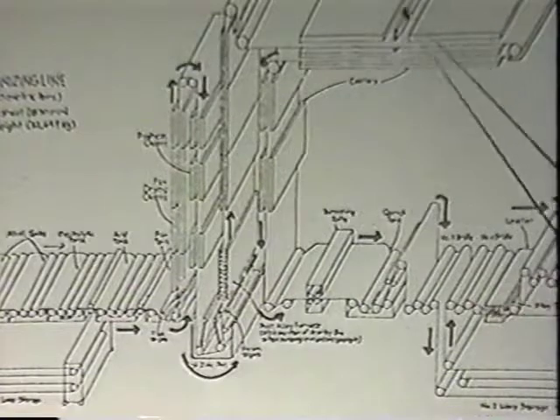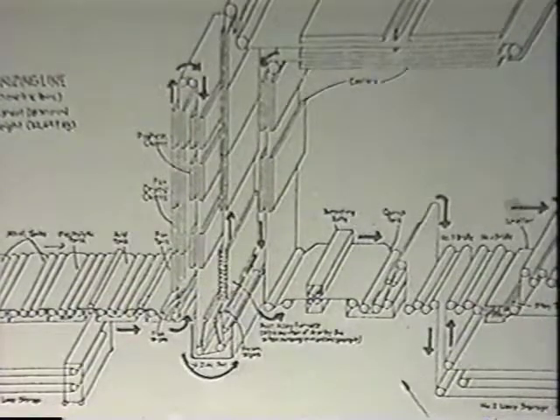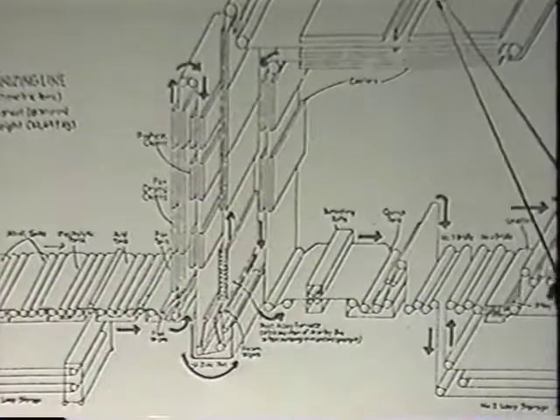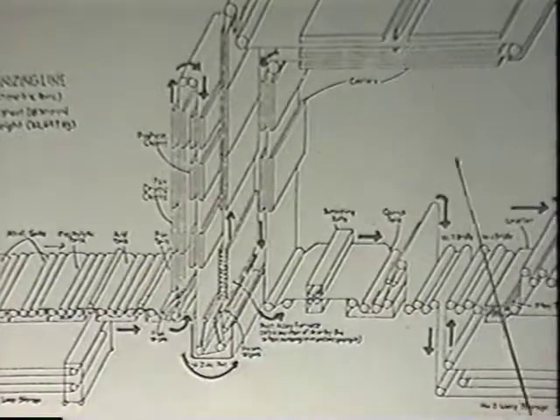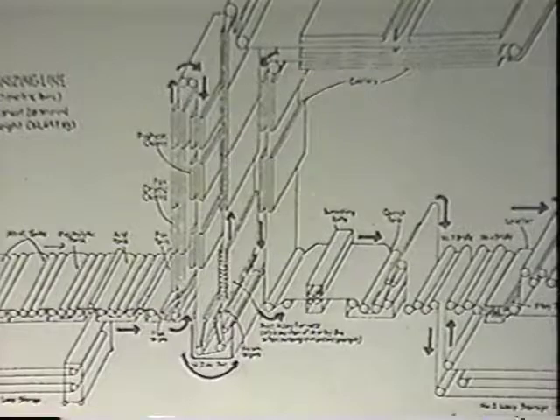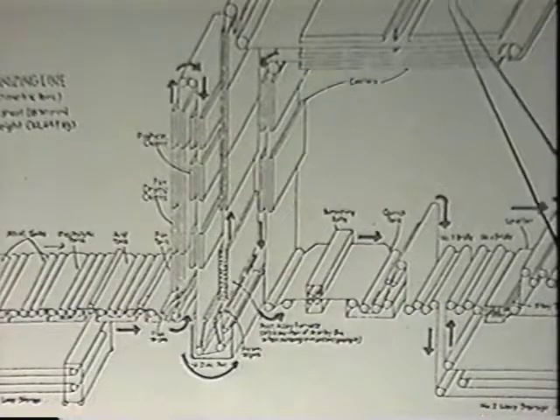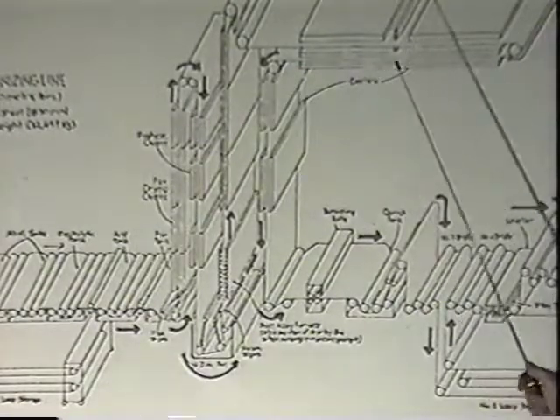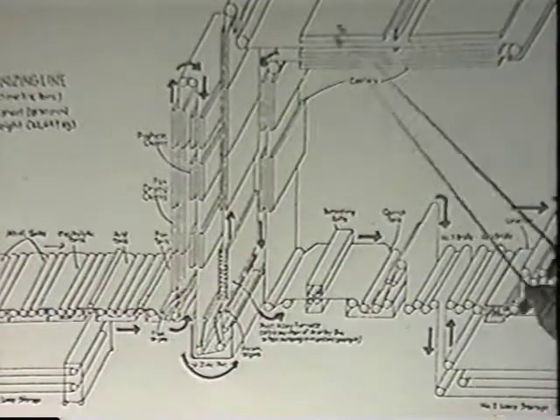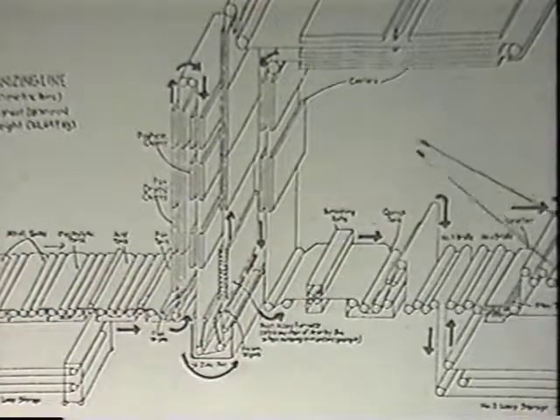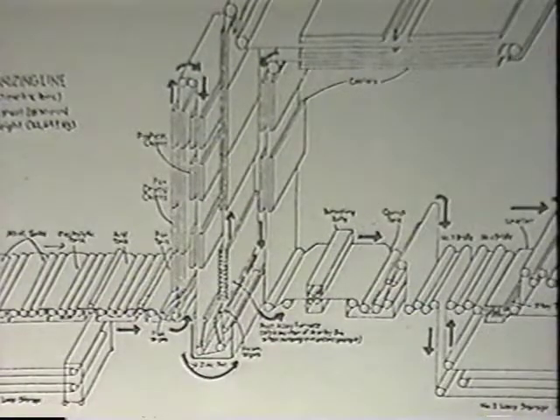Comes up to their coating weight gauge. Every hot dip line in the world's got a coating weight gauge. Not all of them can run galvanneal. This one can't run the coating weight in the percent irons, but does a real good job on galvanized, and they know through the history how to make galvanneal. And that's probably the way it is on 90% of the coating lines across the country. One other thing they don't have is a temper mill. So if they want to put a matte surface on it, they have to send it back to their temper mill again.